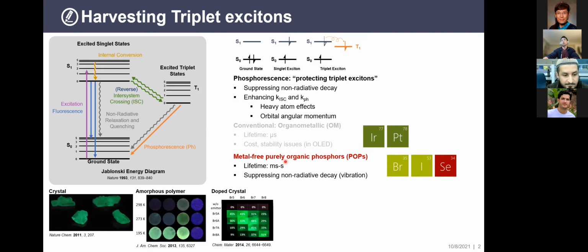And for these materials, because their lifetime is very long, you really need to worry about how to suppress your non-radiative decay. So throughout the previous decade of the development of POP in our group, we achieved a lot of systems to engineer your environment, your matrix, so that you can suppress the non-radiative decay. For instance, when it first came out, we designed crystal systems, and later on we moved to amorphous polymers, which are much easier to fabricate compared to crystals.